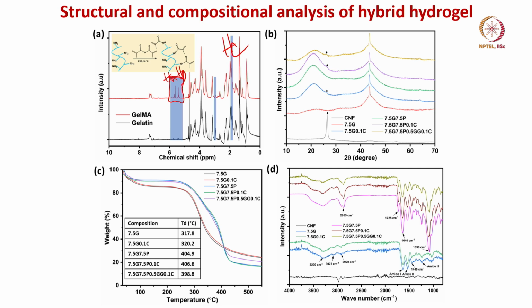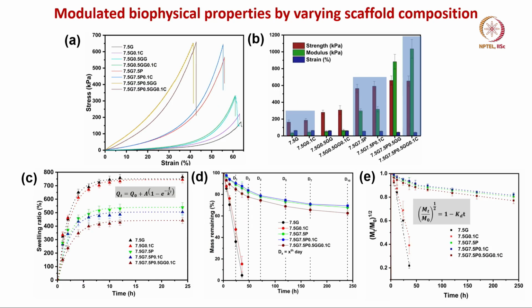appears only in the GELMA. And this is like X-ray diffraction patterns, and this weight loss as a function of temperature, one can calculate by TGA, and this FTIR, FTIR perhaps is more important. You can see certain IR bands which are characteristic for different amides or other phases in this particular case.